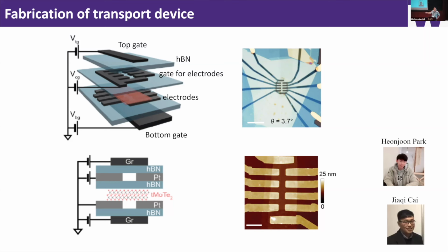The challenge, the reason we don't do transport, is that it's difficult to make good electrical contacts with this TMD device. So the idea we're using is, this is a cartoon of the device. This reddish layer is the twisted TMDs. Then we have a top gate and a bottom gate, and these black parts attached to the twisted MoTe2 are electrodes. So for each electrode contact, we pattern a gate on top of it. You can think of it as a local gate. Then once we turn on these local gates for each electrode contact, we can get a reasonable contact resistance.